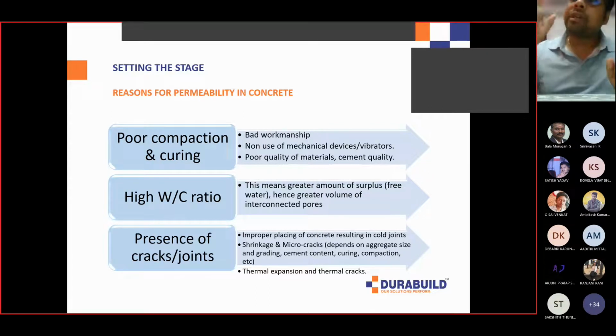So it's possible that they have designed that particular concrete at a water cement ratio of say 0.45. By the time it reaches the site, it has dried out because the site was around 2 hours away from the batching plant. And now the truck driver, he is a big concrete technologist because he's driving the truck, he has the entire power. To save himself from sending that rejected material back to the plant, he will add some water without anyone knowing inside that mixer. So the water cement ratio of the concrete inside that mixer has gone up. These are some real life problems which you will not come across in academics, but these problems happen on site. That is another way through which you are introducing more water, which is a higher water cement ratio, and hence there will be more chances of permeability.